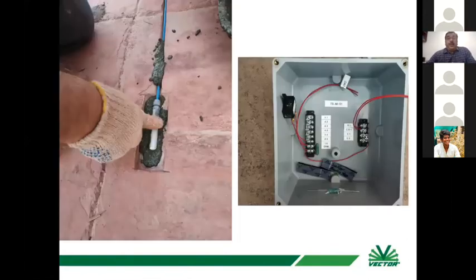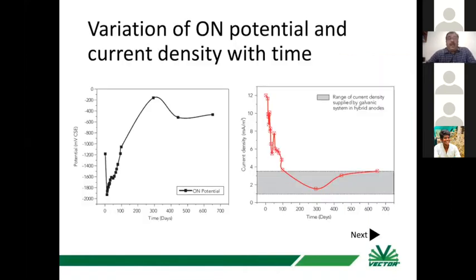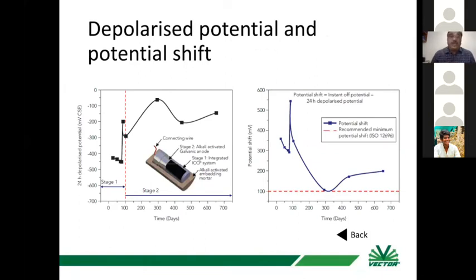Further, we installed the monitoring box, and we are taking regular current measurement and half cell measurement. We found that initially, in stage 1 up to 100 days, there was a very high surge of current, and we got very good negative potentials. Then it automatically converted into sacrificial mode, wherein low current is required, but everything was as per the ACI. It passivated the reinforcement, and the system is working wonderfully. Now the full-stage project is going on for such heritage structure.